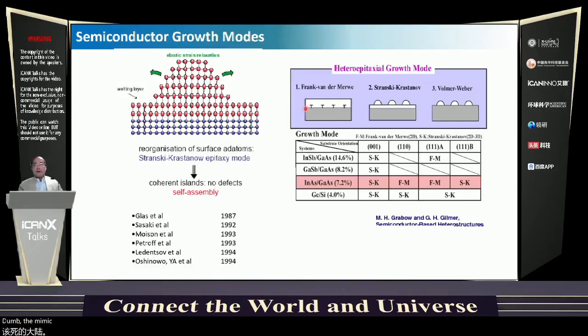The main mechanism for the formation of self-assembled quantum dots is lattice mismatch between gallium arsenide and indium arsenide, which leads to the accumulation of strain surface energy. There are 3 modes for the deposition of lattice-mismatched materials on a substrate. One of them is the Stranski-Krastanov growth mode that causes reconfiguration of surface atoms, resulting in coherent islands with wetting layers. After that group's report, many groups started to try to grow these 3-dimensional structures by the Stranski-Krastanov growth mode.